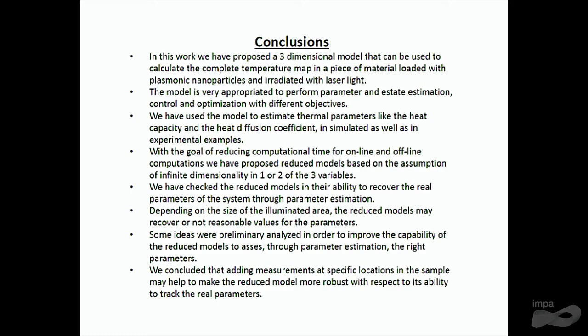Some ideas were preliminarily analyzed in order to improve the capability of the reduced models to assess, through parameter estimation, the right parameters. We concluded that adding measurements at specific locations in the sample may help to make the reduced model more robust with respect to the ability to track the real parameters.